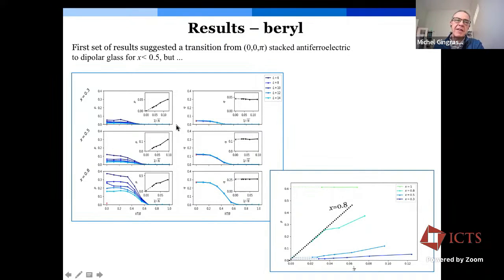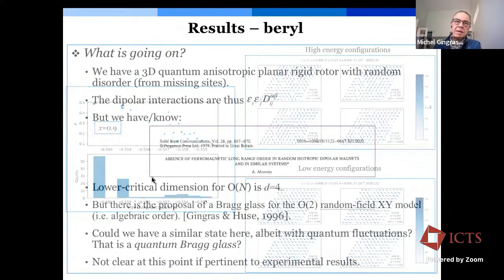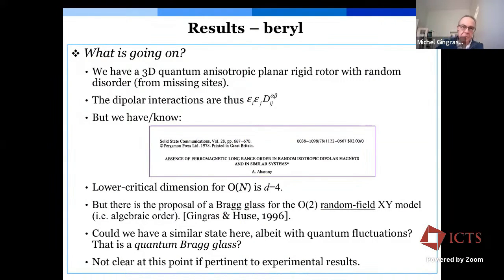So we've explored how the ordered states evolve. This anti-ferroelectric phase evolves as a function of concentration of the cage. And what we are discovering, this is work in progress, is that irrespective of the concentration of the cages, that is, irrespective of what fraction of the cages are occupied by electric dipole moments, we seem to always progressively lose long-range order as the system size increases. And so this is interesting because it reminds us of a well-known result by Amnon Aharony in the 70s, where he argued that when you have systems with off-diagonal anisotropic interaction, the low energy fluctuations away from the long-range ordered phase are infrared divergent below 4 dimensions.